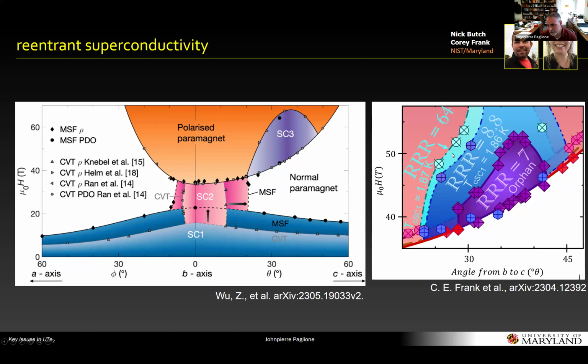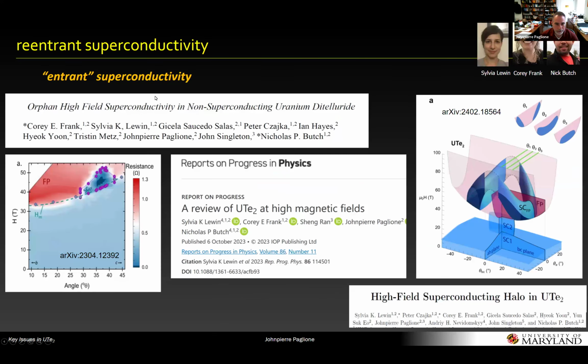So, of course, it's hard to do systematics of this, even at ambient conditions, low field, and so on. But we're trying to do that to understand. But one of the more exciting results from this study was that this sample, with a triple R of 7, so almost the same, doesn't show any superconducting state resistively at low field, but it still shows this phase in this high field regime. So this was deemed the orphan phase. I prefer to call it the reentrant phase instead of orphan, but nevertheless.